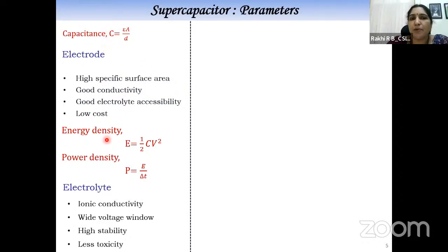Now, the other important parameter of the supercapacitor: we already said that the supercapacitor should have high energy as well as power density value. Energy density is nothing but half CV square, where C is the device capacitance and V is the potential window. And the maximum power density means P equals E by delta T, where delta T is the discharge time. And one more thing I wanted to mention here is that a supercapacitor is a device which can be charged as well as discharged within a fraction of seconds, within 1 or 2 seconds.